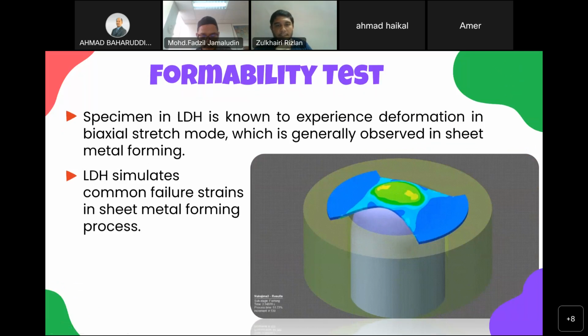For formability test, in my research, I use limit dome height test. Specimen in limit dome height test is known to experience deformation in biaxial stretch mode, which is generally observed in sheet metal forming. And limit dome height test simulates the common failure strains in sheet metal forming process.